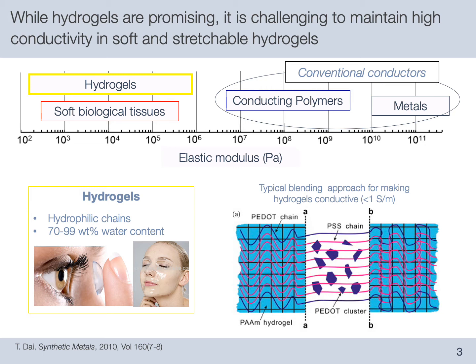We hypothesized that if we could form conductive hydrogel networks completely out of a conducting polymer, then we could deliberately design macroscopically connected networks for charge transport that would allow us to maintain a high water content without relying on a large amount of stiff filler to achieve high conductivities.